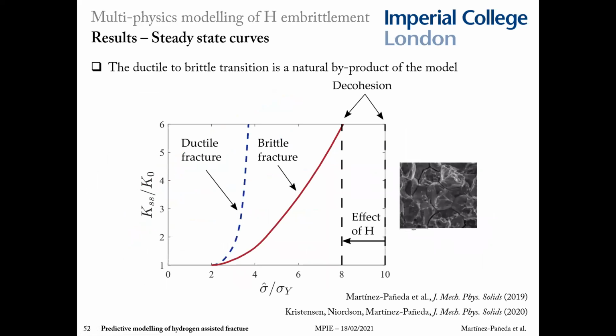So we can plot the steady state fracture toughness as a function of the cohesive strength, and then we get two curves depending on whether we have hydrogen or not. In the absence of hydrogen, the role of plastic strain gradients is small, and consequently the stress elevation is roughly 4 times larger than the yield stress, much below the cleavage strength.